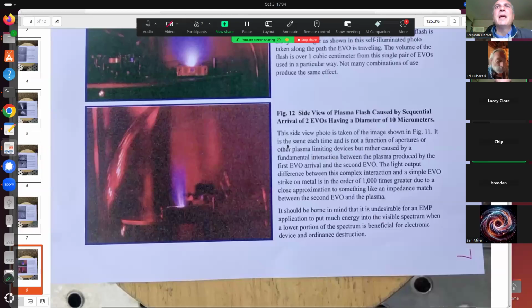It is the same each time and is not a function of apertures or other plasma limiting devices, but rather caused by a fundamental interaction between the plasma produced by the first EVO arrival and the second EVO. The light output difference between this complex interaction and a simple EVO strike on metal is in the order of 1,000 times greater due to a close approximation to something like an impedance match between the second EVO and the plasma.